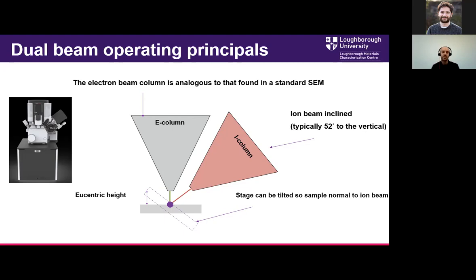What's interesting is that we have the 2 beams at an angle to each other, typically in this case 52 degrees, with a stage that tilts eucentric to both beams. So we can tilt the stage and get ourselves normal to the electron beam or normal to the ion beam. This allows us to cut an area and then image the same area. It also gives us a form of depth perception. By having 2 beams, suddenly we can see the height of a manipulator from the surface, and we can micromanipulate things in a much easier fashion than if we just had 1 beam.